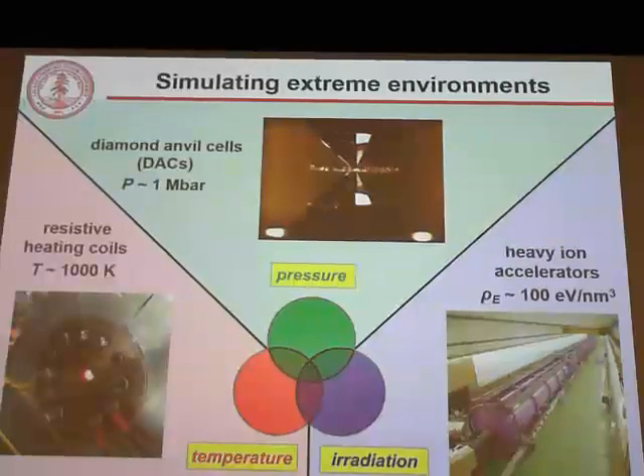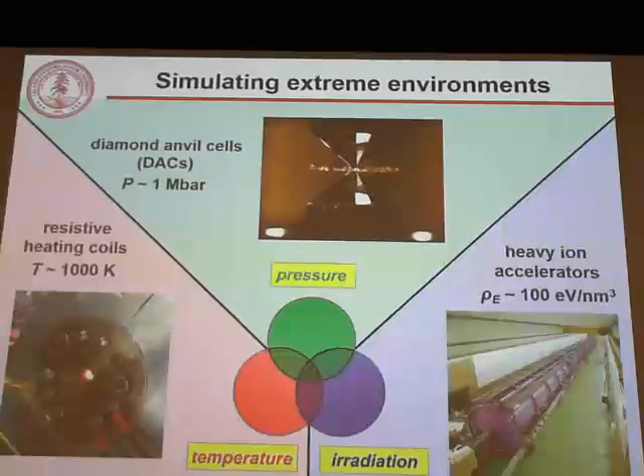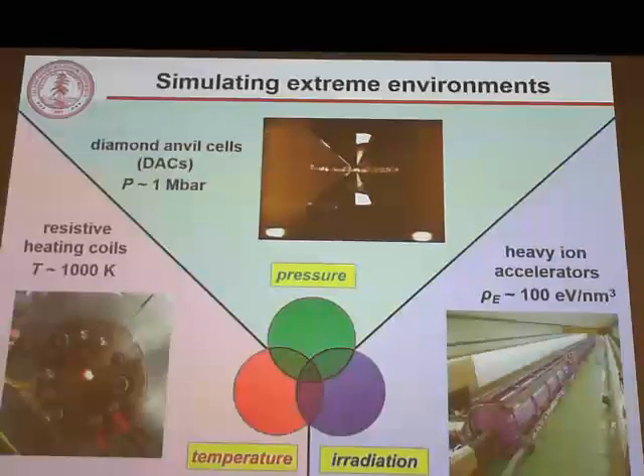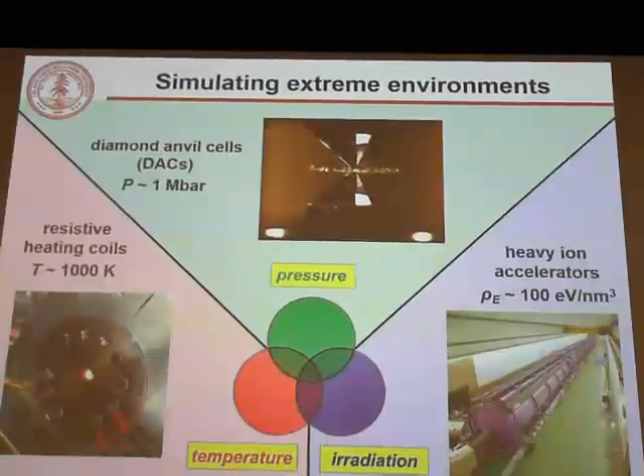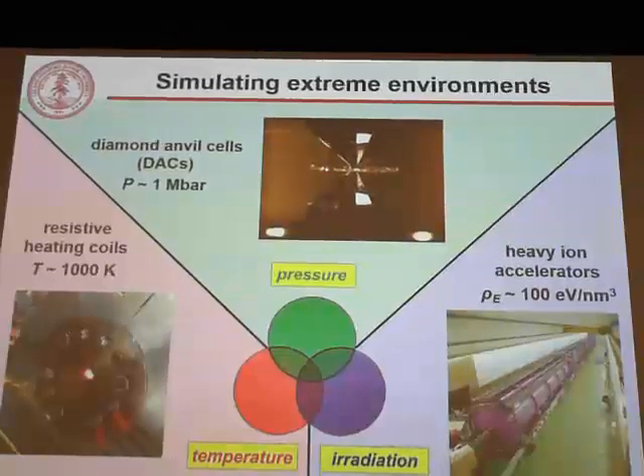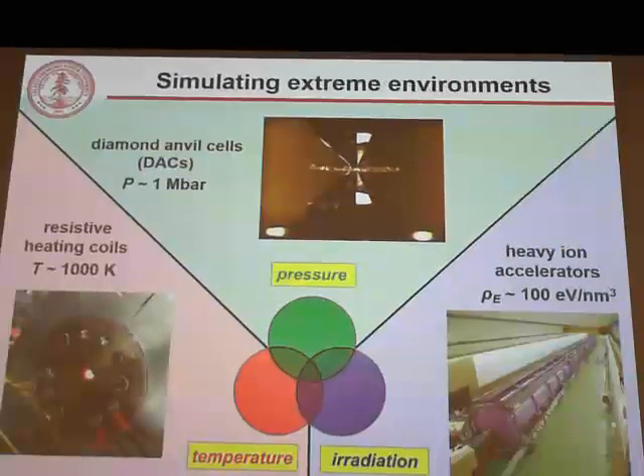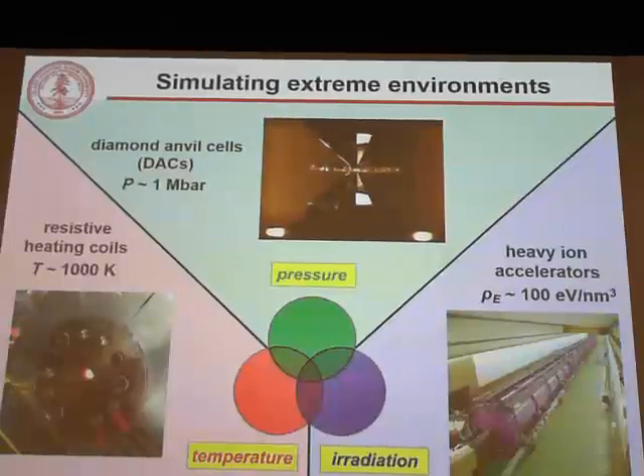So I show here 3 of those extreme environments and the techniques I use to access them in the laboratory. I subject materials to high temperature using resistive heating to get temperatures on the order of 1,000 Kelvin, which is about what you would find in a reactor. Diamond anvil cells are used to get pressures on the order of 1 megabar. In these cells, we squeeze materials between 2 ultra-hard diamonds to compress them to, if we want, pressures up to those found at the center of the Earth. And finally, we use heavy ion accelerators to simulate the effects of fission fragments or alpha particles by irradiating materials with these swift heavy ions, very high mass and high energy particles.